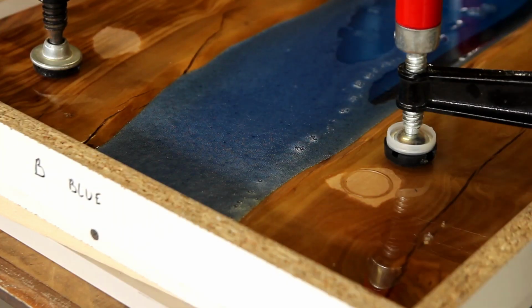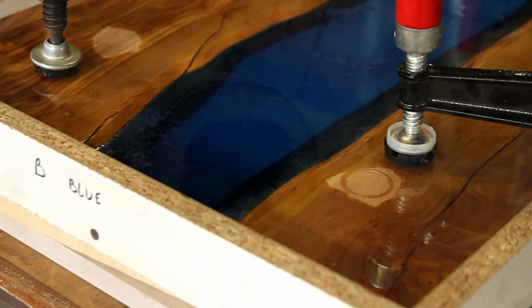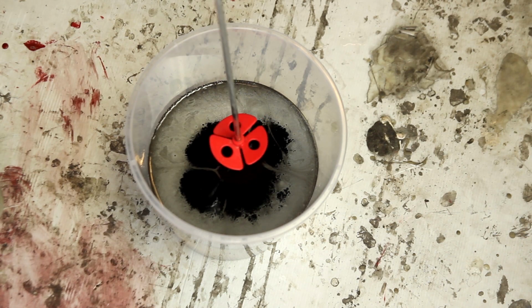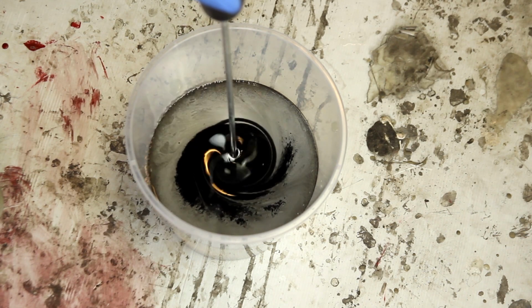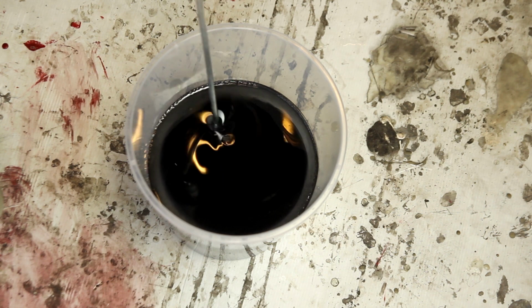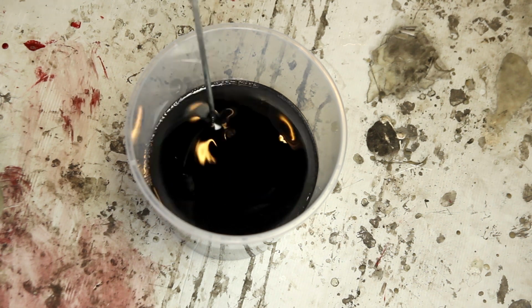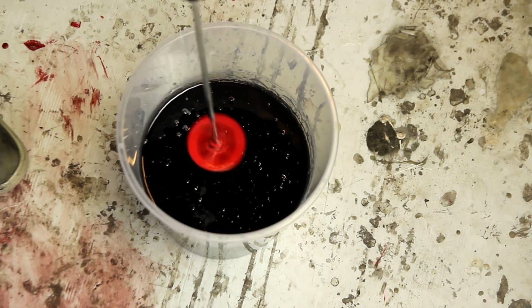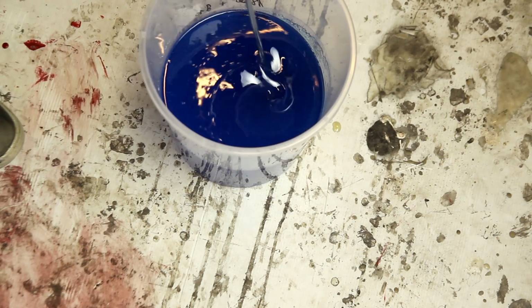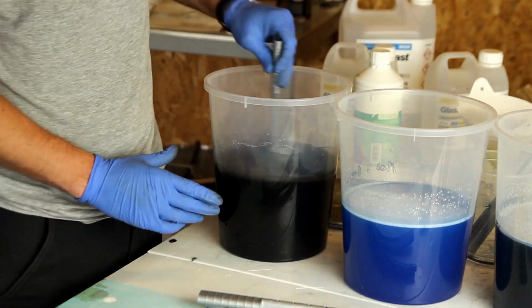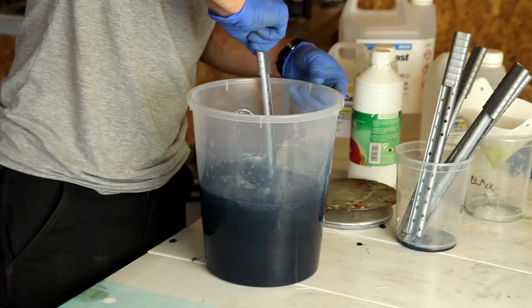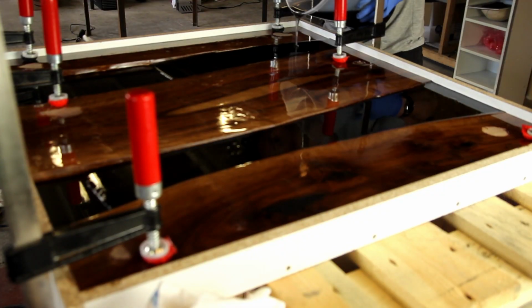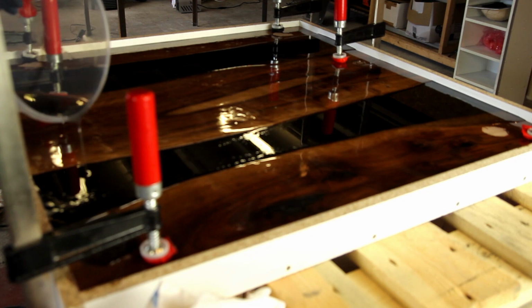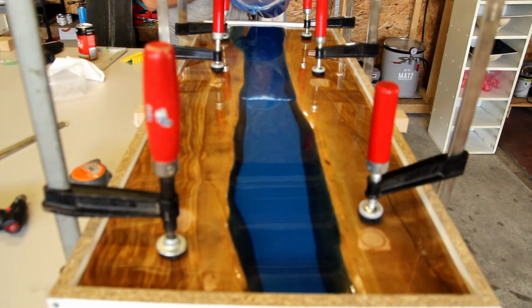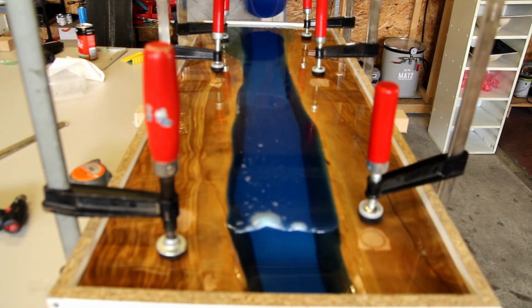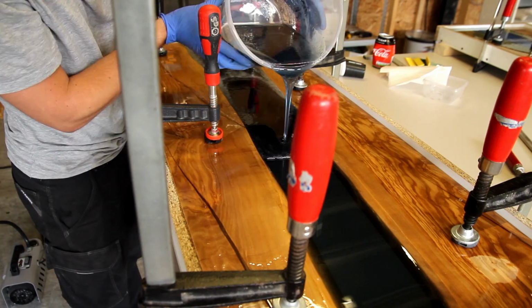This avoids moisture going into your epoxy, which is a second problem epoxy does not like, because it causes the epoxy to bubble. As you can see, the Glass Cast is self-leveling and self-degassing in a way, so it will remove any bubbles over time. You don't need to degas it, though if you can, it's always better to do it. Here I didn't degas it, and as you can see, all the bubbles rise, and then with a heat torch, a heat gun or even a hair dryer, you can remove all the bubbles that are still in your epoxy resin.